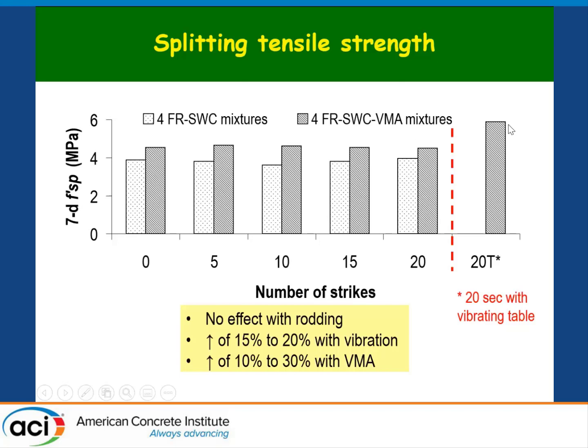And then we have the ones with VMA, in this case, over the vibrating table for 20 seconds. And you can see that there's an increase of 15 to 20% of splitting tensile strengths with the vibration. And especially when you have VMA, you have an increase in vibration, in splitting tensile strengths.